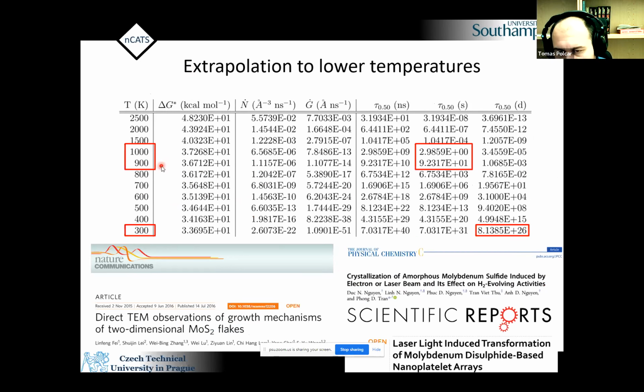And the typical sliding temperature, if you slide macroscopically molybdenum disulfide under certain contact load and so on, is about 900-1000 Kelvin, which seems quite high. But if you really imagine that you have some asperity contacts, this is typically what you get. And our simulations say that about half of the material will crystallize in a certain volume in a matter of seconds, or let's say up to 1 minute. And this is actually what we observe experimentally. And another indirect proof is that at 300 Kelvin, amorphous material like molybdenum disulfide will never crystallize. This is what we know from experiment as well, because the time is almost infinite here.